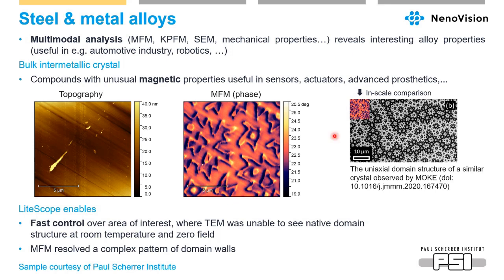We measured the topography first of a bulk intermetallic crystal, and it has unusual magnetic properties. It's useful in sensors or advanced prosthetics. And we can see that it's smaller because a bigger area of interest was measured. In the magneto-optic Kerr effect, we see the same structure. So with LiteScope, we were able to quickly control the area of interest, and where TEM was unable to see the native domains at room temperature, MFM resolved this complex pattern quite easily.